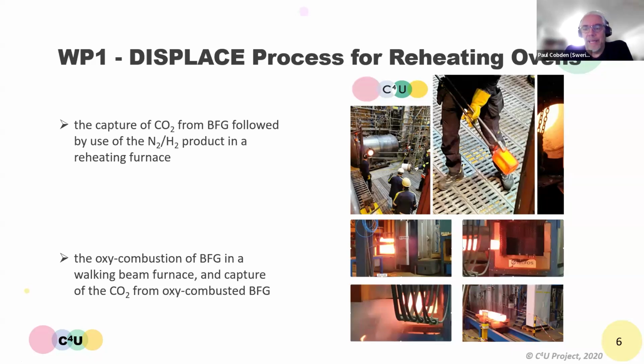At the top, what you see is an alternative way of decarbonising the reheating ovens, and that's to remove the CO2 and the CO from the blast furnace gas, which results in a nitrogen hydrogen product, and then to use that for reheating of the samples. So this was a world first, as far as I know, in terms of reheating using recovered hydrogen from a blast furnace to reheat steel.